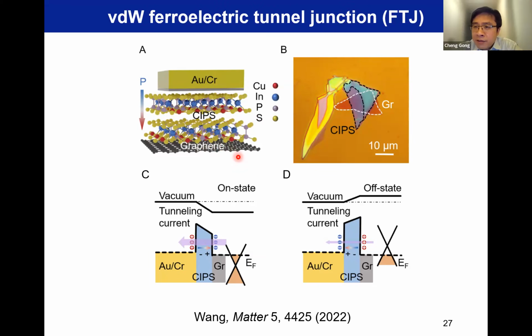So you can imagine they have different work functions, and then you can use the ferroelectric polarization of this spacing layer to either reduce or enlarge the difference of these two chemical potentials, and you can realize the so-called smaller or larger tunneling barrier. Compared with the traditional ferroelectric tunnel junction based on oxide, there are 3 advantages here, potentially leading to the very huge tunneling electroresistance we observed, at least 4 orders of magnitude higher than the traditional oxide-based ones. And they are at room temperature. Our demonstrations are at room temperature.